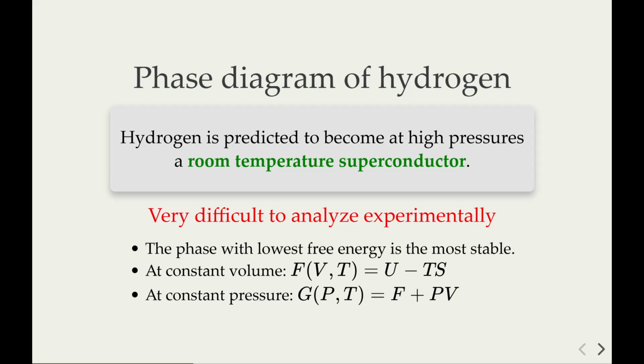So we really need to rely on indirect measurement to characterize the phase diagram, like how the Raman spectrum changes when we change pressure, or how reflectivity of the sample changes when we change pressure - very indirect ways of measuring the structure of this system.